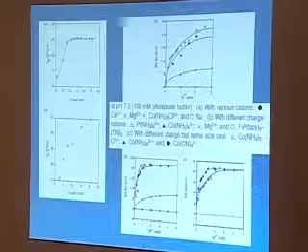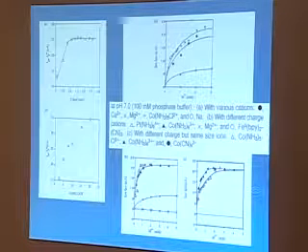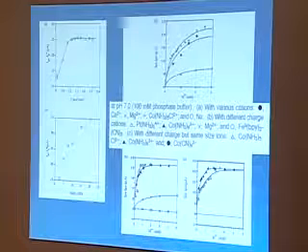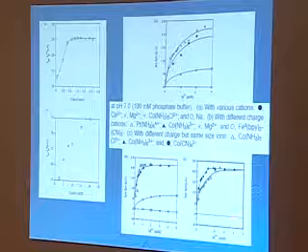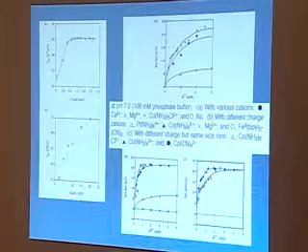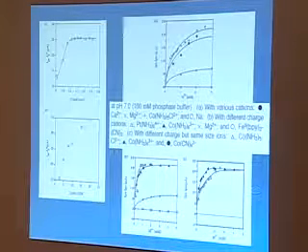Let's look at a series of cobalt ions here: the hexamine, the chloro, and the cyano, which would give us a negative charge on it. We want to see if it's the cobalt for some reason, or is it actually the charge? Again, if you have a negatively charged species around, there's no catalysis, and the more charged, the merrier. Here's what that's showing: the higher the charge, everything else being the same, the better off you are. So cationic charge is important in this system.